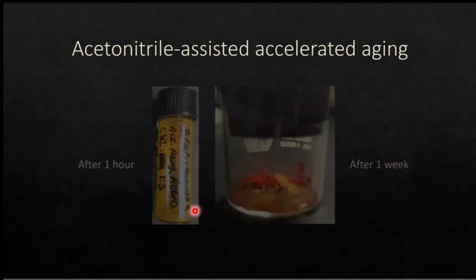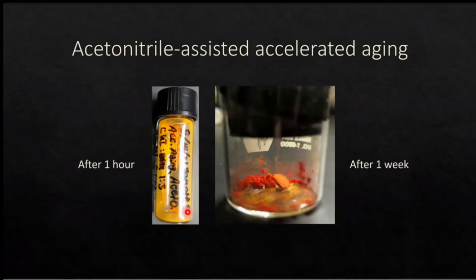So then we wanted to see if acetonitrile would behave the same way in an assisted accelerated aging process. And so when we did this, we found that after 1 hour, we had formed this bright orange polymorph, and that it took around a week for this to mostly turn red. But even at 1 week, it was still a mixture of orange and red, which you can't see very well in this picture. But remember that with water, this only took about 30 minutes. And so the length was much longer with the acetonitrile.